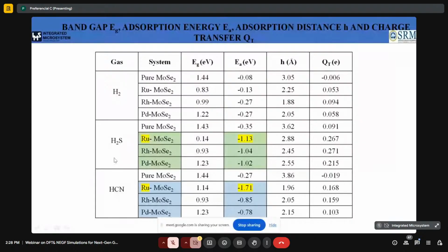Whereas if we come to the H2S gas adsorbed systems, compared to pristine, all the doped systems are showing better adsorption towards H2S gas, which implies the doped systems are enhancing the adsorption phenomena for gas sensing. And out of all these, the ruthenium doped system is showing a very good adsorption, the lowest adsorption energy with a negative magnitude, that is minus 1.13. This will be a good adsorbing system towards H2S gas, and this also shows a good charge transfer value.